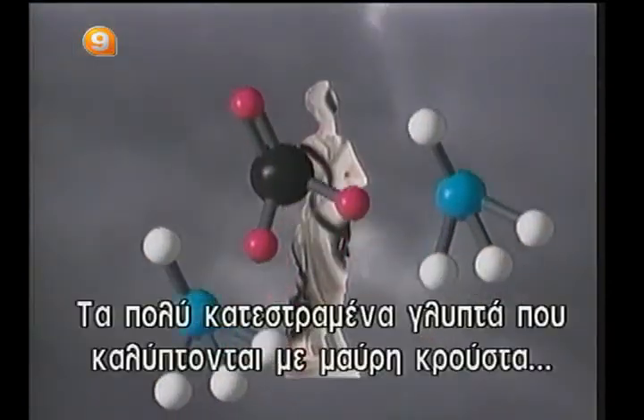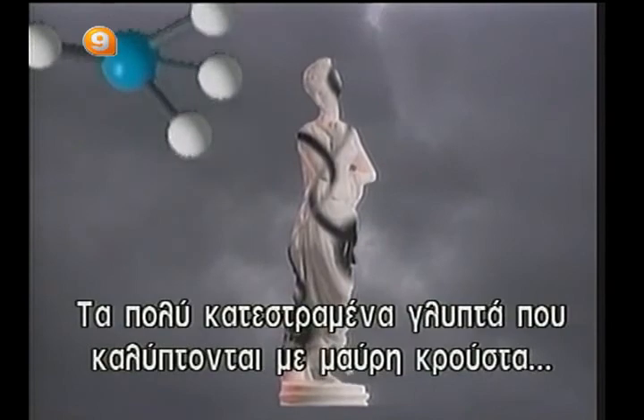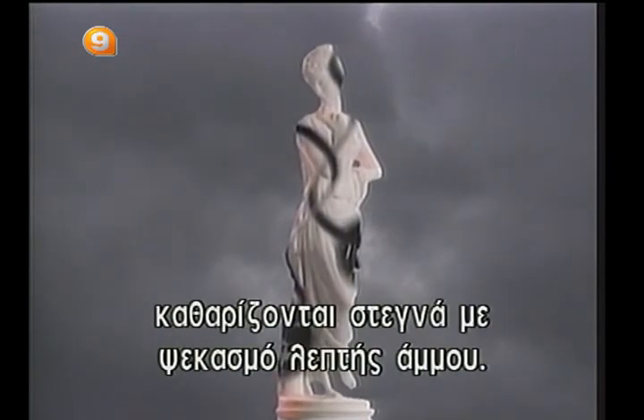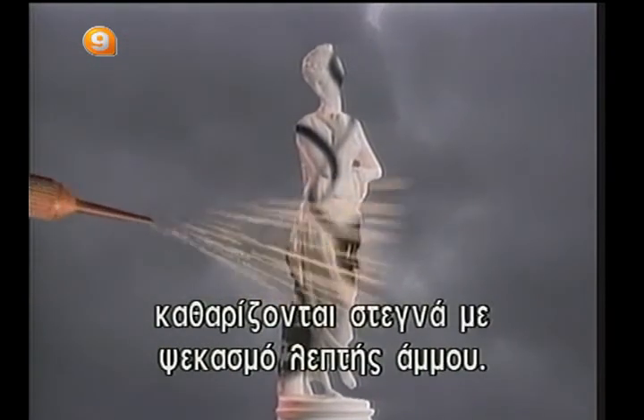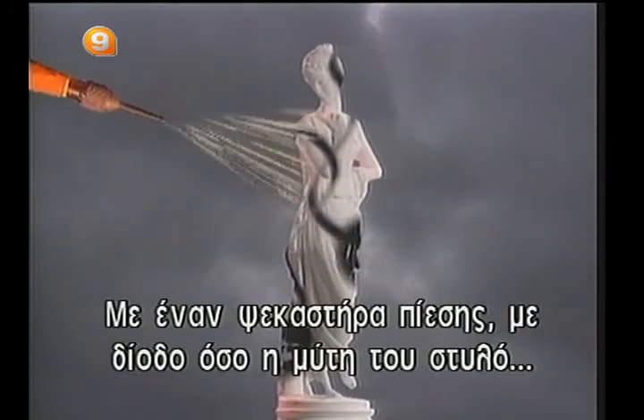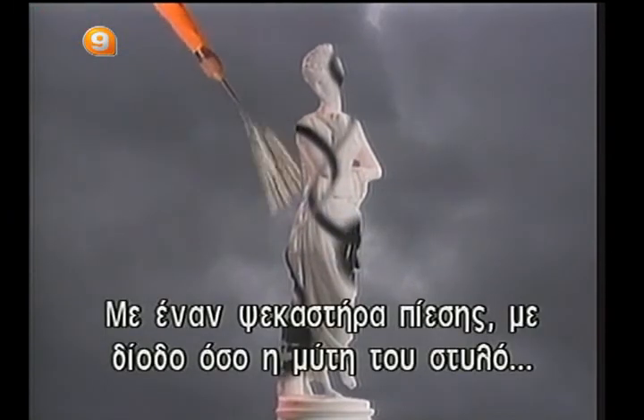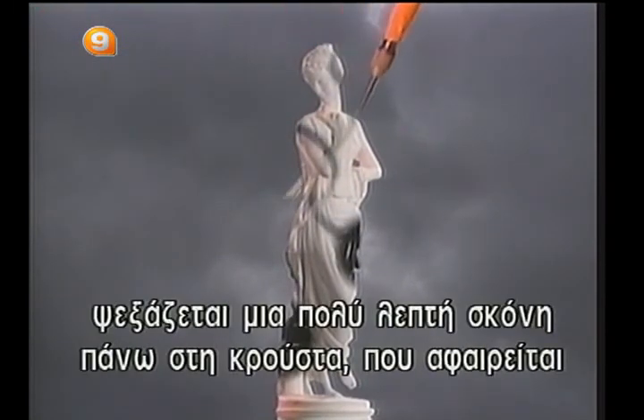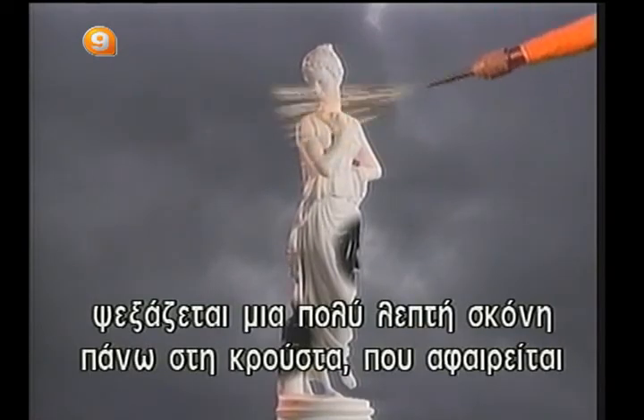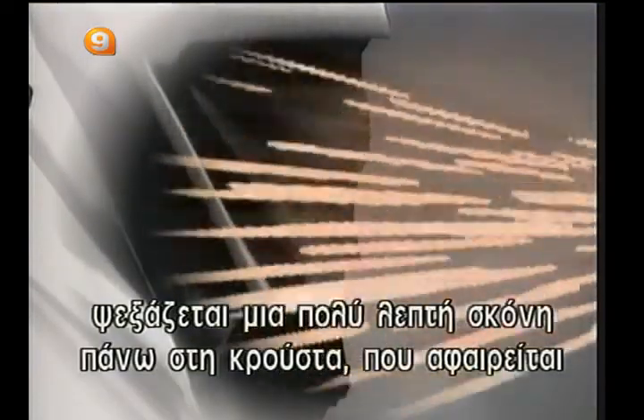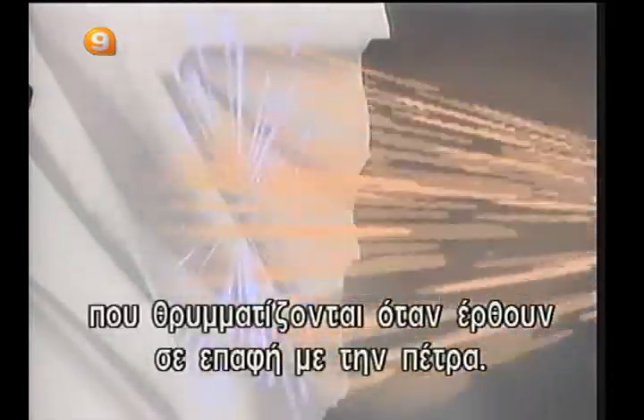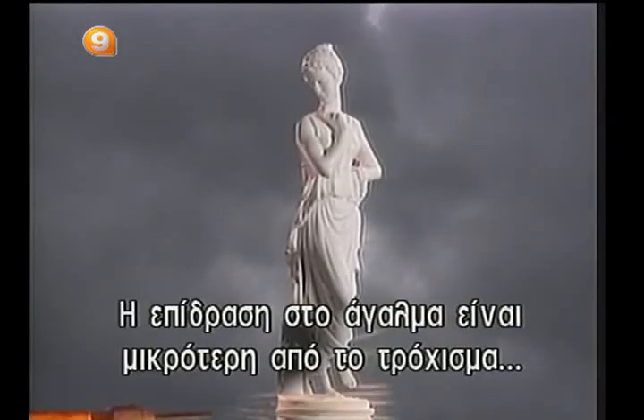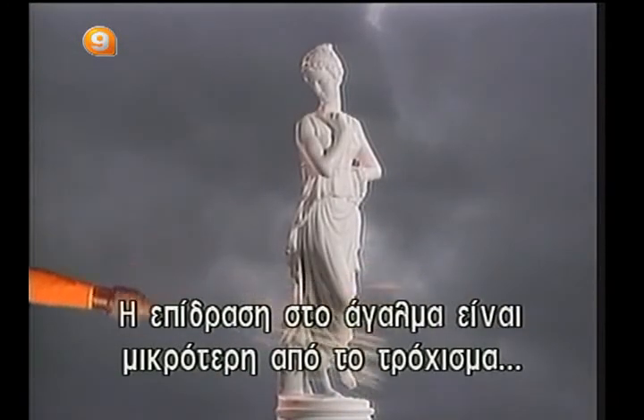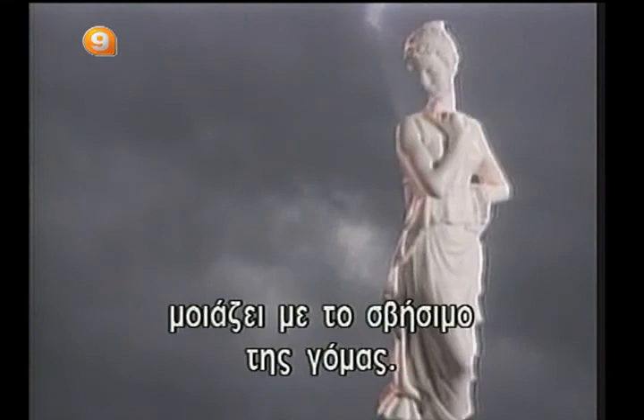Badly damaged sculptures covered in layers of black scale are generally dry cleaned by fine sandblasting. In a pressurized stream no larger than the nib of a pen, a very fine abrasive powder is sprayed directly onto the scales to be removed. The powder usually consists of minute glass beads that shatter on contact with the stone. The effect on the statue is less harsh, not like a real abrasion, but more like the rubbing of an eraser.